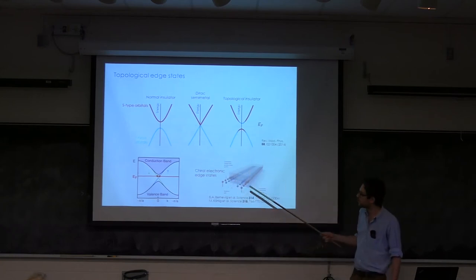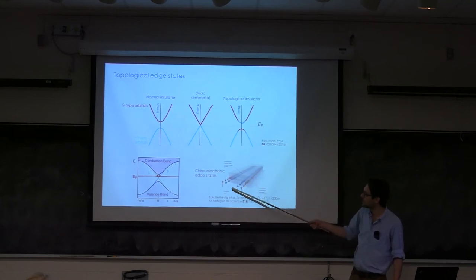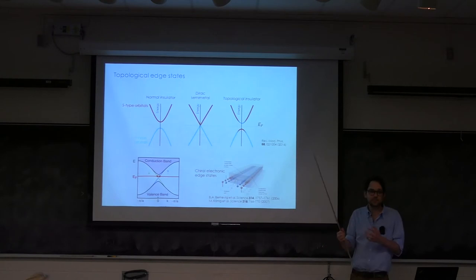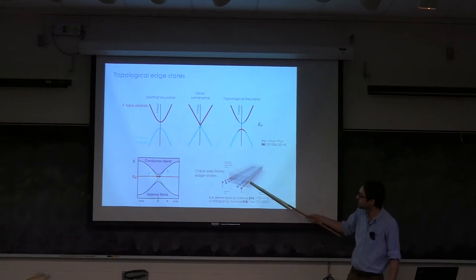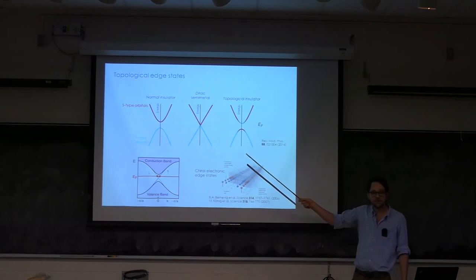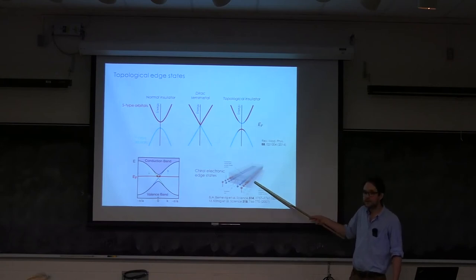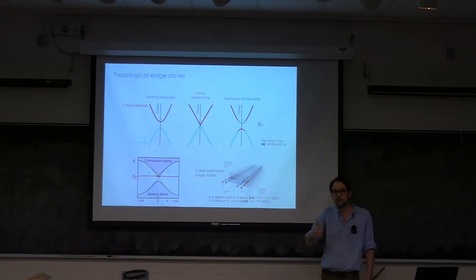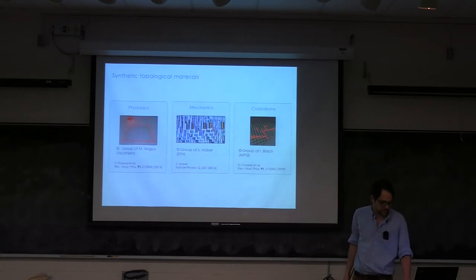All right, so here I'm just showing the first example of such a topological insulator that was realized in a material with very heavy elements, mercury and tellurium, to have this strong spin-orbit interaction. And as a result, people really did observe at the interface with vacuum, vacuum can be considered a conventional insulator, at the interface exactly spin-polarized unidirectional electronic modes moving in one direction, and that can circumvent, contour any defect. They are robust to perturbation.